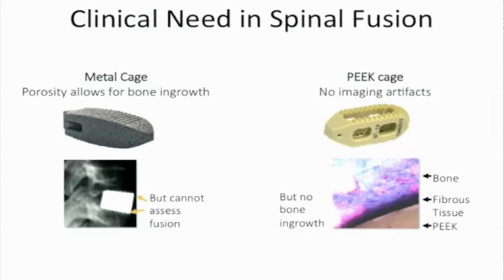The real problem with the metal cage is it doesn't image after that, particularly with an MRI. So if you go in and say, I have back pain, they image you and they say, wow, one of your discs is in a bad spot. They fuse it, you come back and say, it still hurts. They're like, well, we can't image that spot anymore. You can't see what's happening anymore. So surgeons moved away from metal cages because diagnostics is such an important part of this.